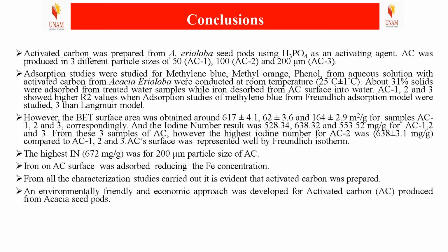Adsorption studies were conducted for methylene blue, methyl orange and phenol from aqueous solutions with the activated carbon prepared from acacia seed pods, at room temperature, 25 degrees centigrade plus or minus 1 degree, and about 31% of solids were adsorbed from water samples, while iron got dissolved from AC into water.